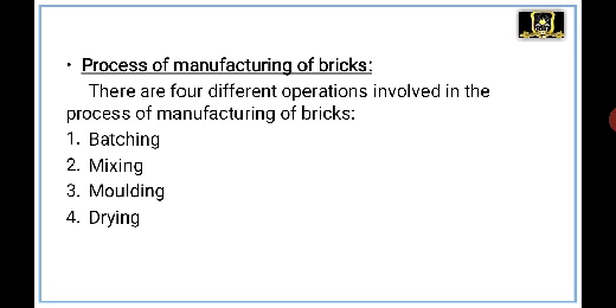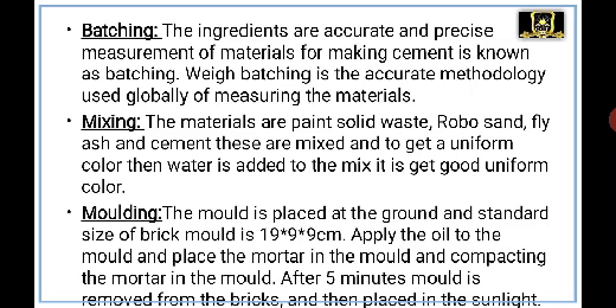Process of manufacturing of bricks. In manufacturing the bricks, there are four different operations involved, which are listed below: 1. Batching, 2. Mixing, 3. Molding, 4. Drying. 1. Batching. The accurate and precise measurement of the ingredients for making the mix is known as batching. 2. Mixing. The materials used are paint solid waste, RoboSand, fly ash, and cement, mixed to get a uniform color, and then water is added to it. Third, molding. The mold is placed on the ground and the standard size of the brick mold is 19 by 9 by 9 centimeter.